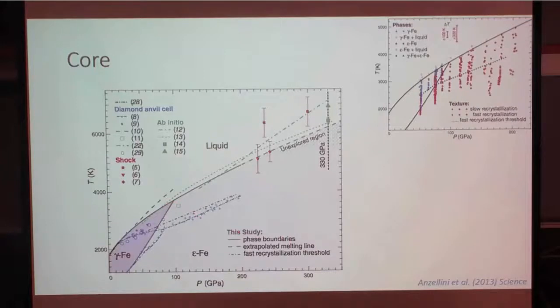Another nice thing they did in this study is that this is the old melting curve of Boehler, some of you may be familiar with, where he identifies melting as a change in the apparent motion of the material. What these guys noticed is that they still had X-ray diffraction above this point, but they get rapid recrystallization happening along this line here at a temperature and pressure condition that agrees very well with what Boehler identified as melting. So what Boehler identified as melting is probably not melting, it's probably just this onset of rapid recrystallization. So that sort of explains that discrepancy.